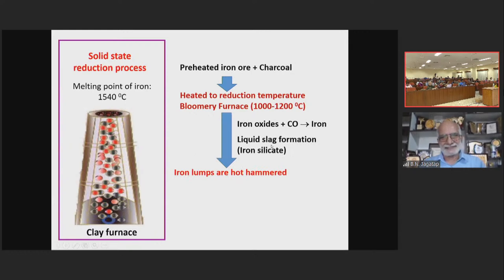And therefore, this is the solid state reduction process. What happens in this process is that carbon monoxide is produced because of the incomplete combustion of charcoal. This carbon monoxide reduces iron oxide and produces iron. However, there is a lot of silicate in the ore, and that combines with iron and forms iron silicate. This is called liquid slag. So, at the end of this, you get iron with the liquid slag. These iron lumps are then hot hammered so that the entrapped liquid slag is released from the iron mass, and what you get is wrought iron.